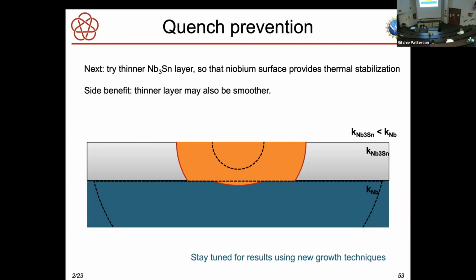And the way to do that is to use thinner layers of niobium-3 tin. It does not conduct the heat away well, but niobium does. And so if this layer is thinner, you can absorb the heat before it causes a quench. So that's the main area of research in niobium-3 tin today, is to make thin, smooth layers.